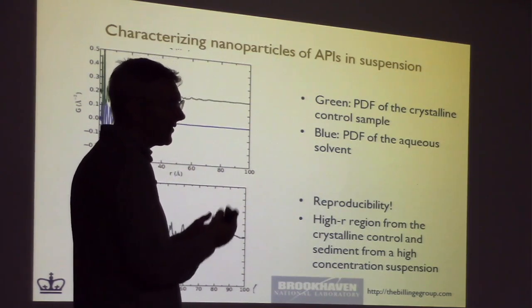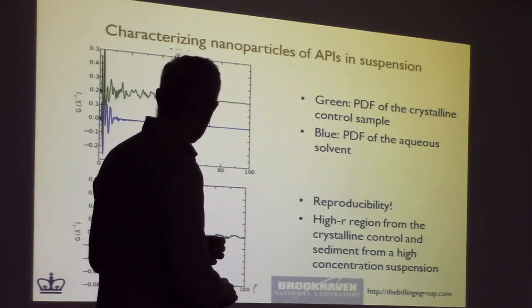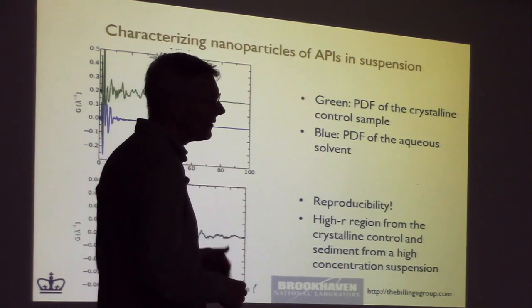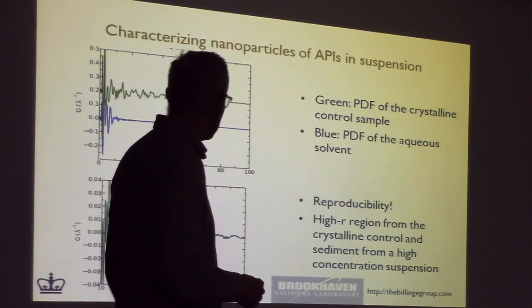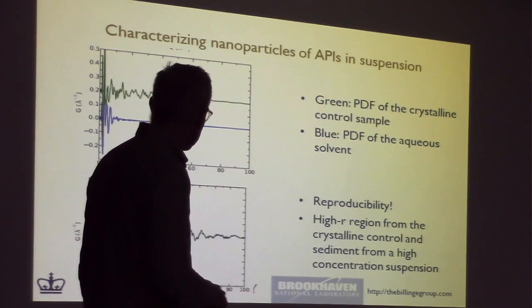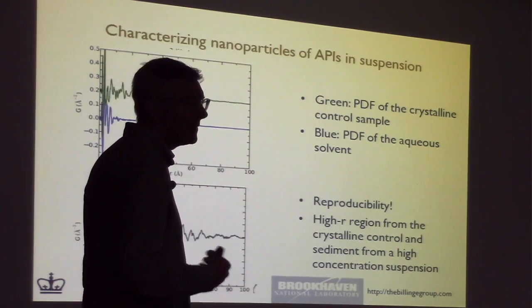So it was made in too high concentration and precipitated out. And you can see that the material precipitated out is the same as the control. And this is the level of reproducibility that our measurement has. So we're very confident that we're really measuring the drug.